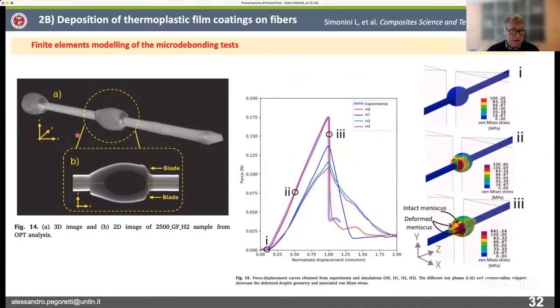These are basically 3D images taken by the optical microscope, which is on the equipment. And by this, we were able to reconstruct exactly the geometry and to model the geometry by using finite element method. The results are summarized here. It is quite interesting to see, first of all, that the predictions, which are the continuous curve, are following the experimental data very nicely. So we can reproduce the experimental data.